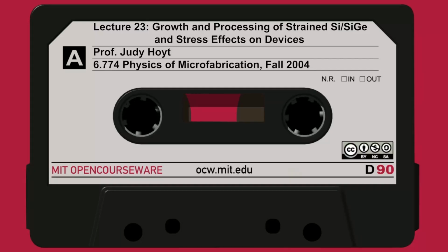And in fact, on page 45, what you see is that the strained silicon is bonded to the oxide. It's low defect density material, and if you do Raman scattering, the strain remains. Even after you remove the silicon germanium, and you anneal it at high temperatures, even up to 1,000 degrees, the strain doesn't go away. So the bond is very strong. So now you have strained silicon directly on insulator. It looks just like SOI. You can process it just like SOI, but the strain is already built in. You don't have to add any germanium that you need to worry about. So I think that's going to be a pretty interesting area for the future.